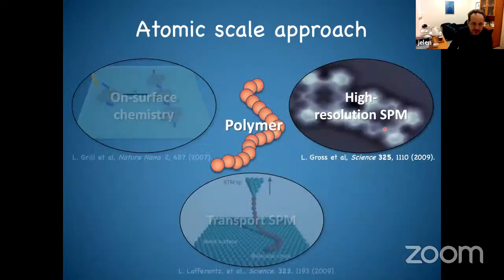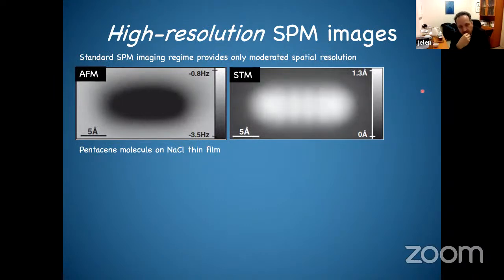And on top of that, of course, we can also use the recent progress in scanning probe techniques, so that these days we can see the chemical structure directly. Let's say 10 years ago, when you talked about scanning probe microscopy, it was great, you could see atoms, but from the perspective of chemistry it was very difficult, because the best images were these kinds of ovaloids that you see here. This is either atomic force microscopy or scanning tunneling microscopy. This is a known molecule, you know what you deposit, it's pentacene. But this is the best image you could get using the standard STM technique.